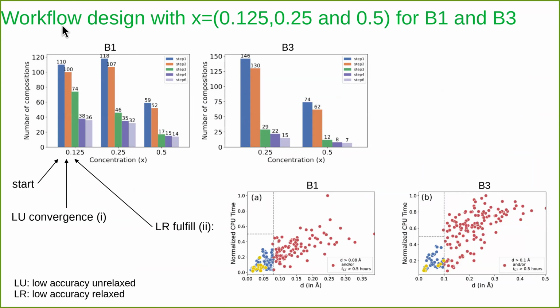So let's say we took a B1 alloy, a sodium chloride structure alloy. We created the SQS supercells, and we set up the concentration 0.125. In the first step, we generated 110, let's say, candidates. Then we did the low accuracy unrelaxed calculation. Only 100 passed the convergence; 10 of these candidates are not converging. And then comes the next step, where we actually do the relaxation.